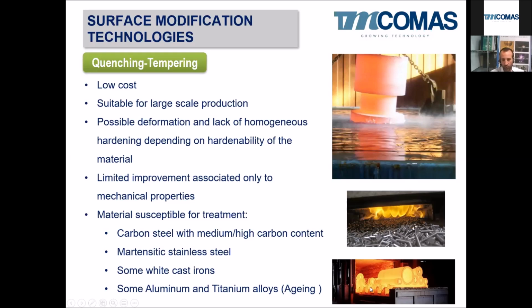Or here we can use one furnace to place a lot of different shapes in the same heat treatment. So with quenching and tempering, it can give possible deformations to the materials. Also, there can be some lack of hardening homogeneity depending on the hardenability of the material. Not all materials can be hardened to the core. Some of them have an exact composition to increase the hardenability. It means the depth to which quenching can affect. So this has to be taken into account.